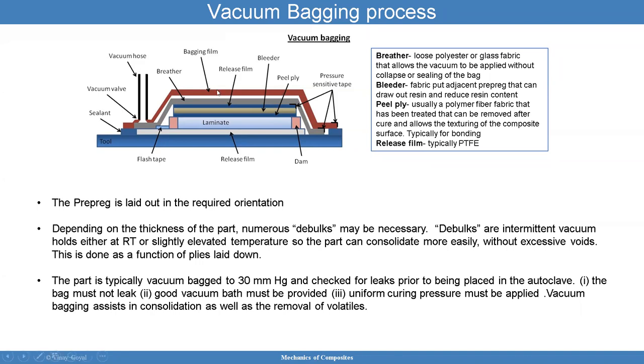And then you have the peel ply. You can see the peel ply right there. It's usually a polymer fiber fabric that has been treated, that can be removed after cure, and allows texturing of the composite surface, typically for bonding. And finally, I have the release film that I talked about earlier. It could be a Teflon, for example. So we don't want things to get stuck.